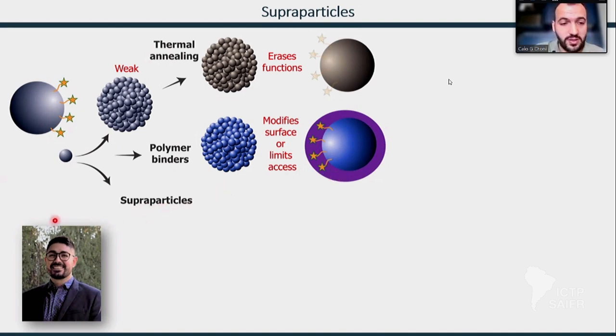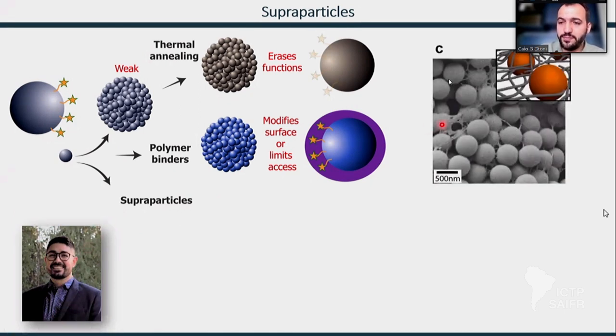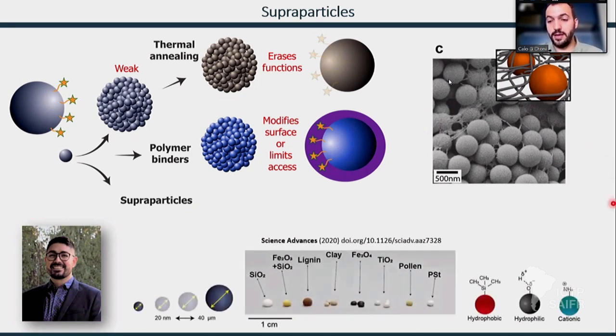In the case of supraparticles, there is this beautiful work from Bruno, a colleague from Finland, showing that we can have the particles interlocked by cellulose nanofibrils without hindering the functionalities, right? He proposed a universal interlocking mechanism for particles from 20 nanometers to 40 micrometers, cationic, anionic, hydrophilic, hydrophobic, polymer, inorganic, organic, bound together by cellulose nanofibrils upon drying and interlocking on top of a superhydrophobic substrate.